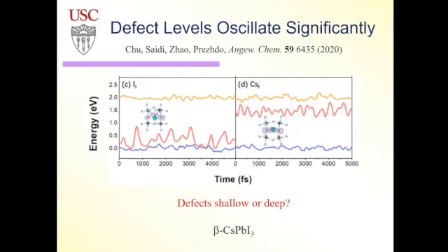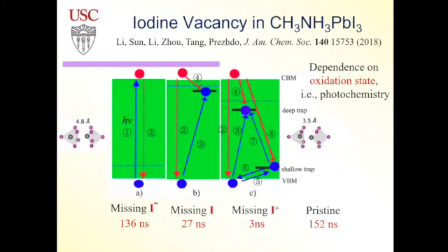So this whole terminology that people use in inorganic semiconductors, shallow traps, deep traps, doesn't really apply here, because the same trap could be shallow or deep depending on time. So you have a whole distribution of energies of the trap state. And this is true of most of the trap states. This one is deeper, but still there are some times where it's quite shallow and then the charges can escape. So that was shallow, deep, and dynamics is very important.